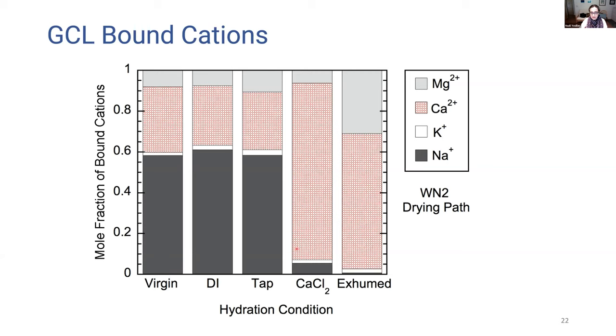So what we have here is for virgin material and DI and tap water exposed material, relatively similar mole fraction of the bound cations, which are dominated by the sodium in the system, which is the original product, the material that is produced in the first place. More than half of the bound cations, reaching levels of 60% or so, is sodium. There is some calcium in the system, as well as some potassium and magnesium as well. When we look at the other two, the WN2 products here, after exposure to the calcium chloride solution and the material that's exhumed from the field, we see that the bound cations have changed significantly.